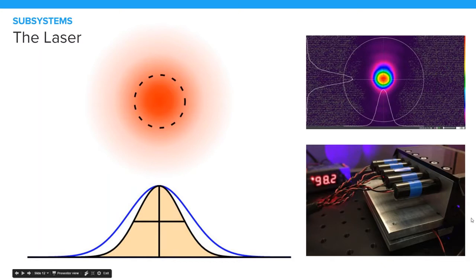This is actually really important because when we design our galvo control mechanisms, we take this into account so that when the laser passes over each beam path, we're spacing them so that the beam can not only cure the current layer, but part of the previous layer as well. And that gradient is one of the main reasons why SLA print processes have such a smooth finish versus FDM, where it's a hard on-off sort of thing.